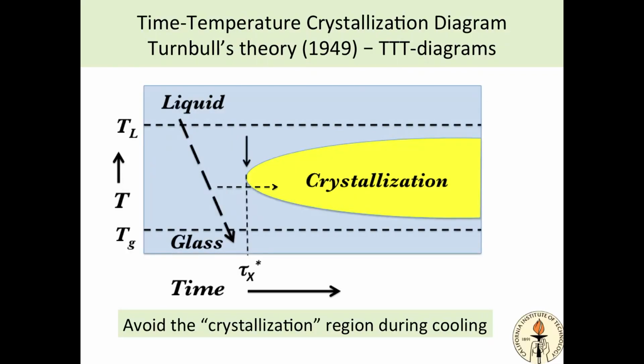So my advisor here at Caltech, okay, let me sort of depict what I'm talking about. Here's a liquid, that's the melting point. So the liquid is stable up here. It's the equilibrium state. That's like the melting point of ice. And if we cool the liquid down far enough, it sets up and vitrifies, becomes solid. That's a glass, right? And that's called the glass transition, where it sets up. And we have to get from here to here before we get to there. And that's the time it takes for a crystal to form in a cubic centimeter or some volume of liquid. That's Turnbull's theory in a picture.